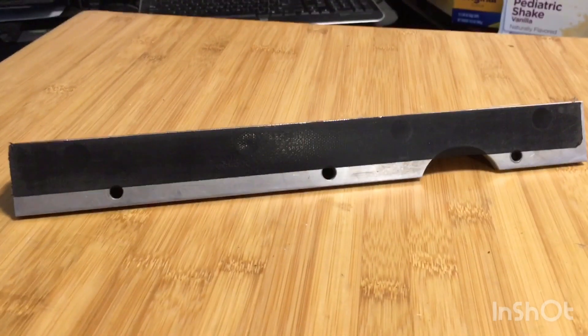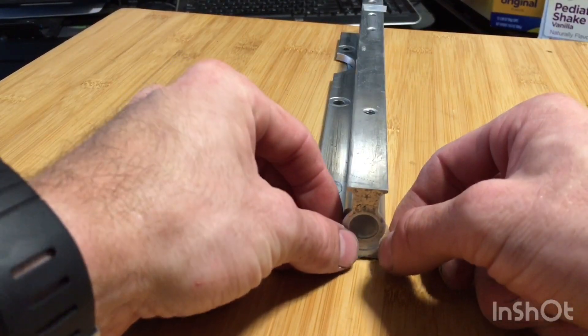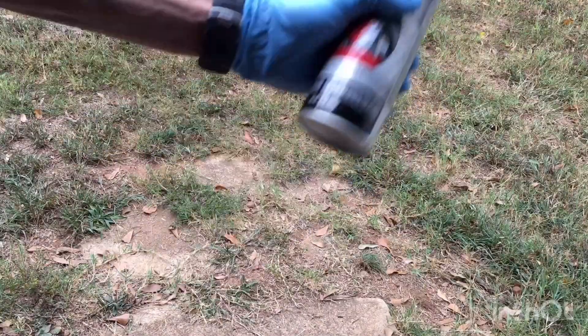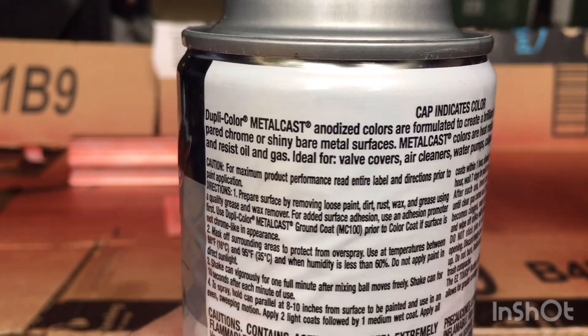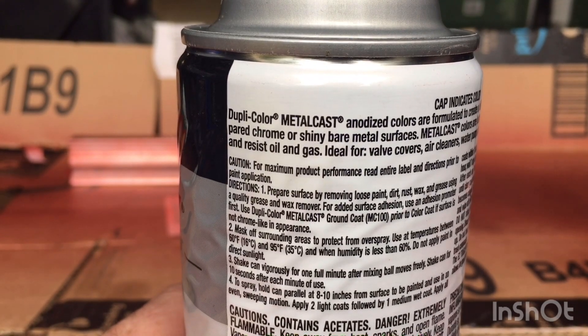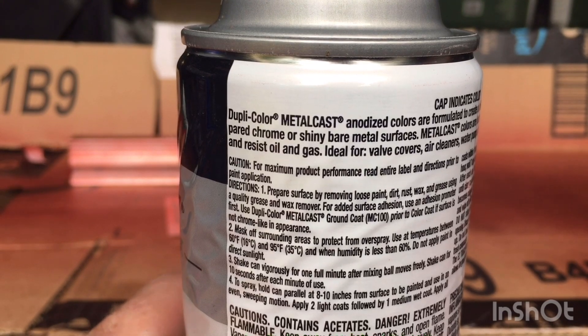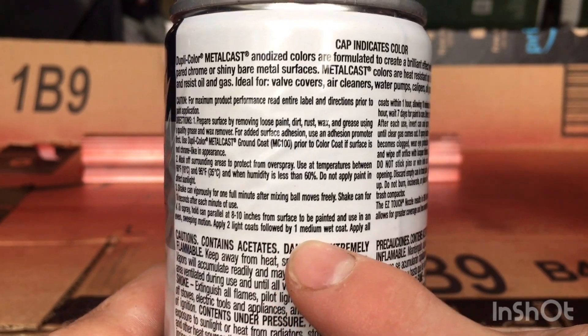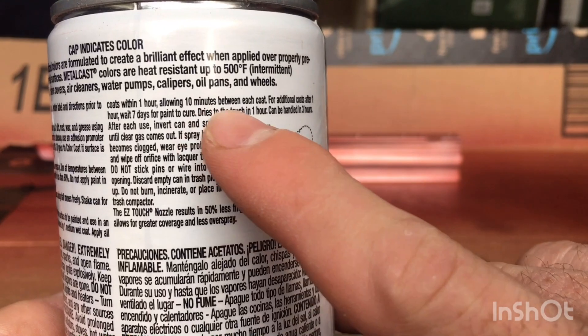I ran a piece of duct tape on the bottom side. According to the directions, you need to prepare the surface, make sure that it's between 60 and 95 degrees outside and humidity less than 60%. Then two light coats followed by one medium coat — apply all the coats within an hour, allow 10 minutes between each coat.